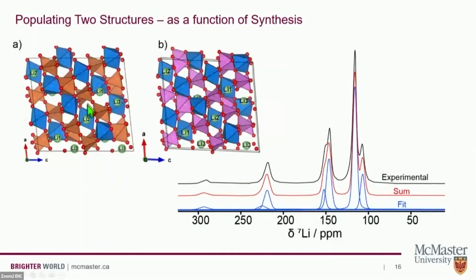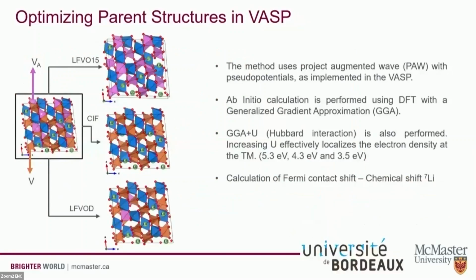The orange one is the original CIF file from our collaborators in Montreal, and the pink is if we fully populated this new set of sites that Tiana had determined in the crystallography. So in order to understand why those chemical shift differences are happening, we rely on VASP, and this is in collaboration with Danny Carlier's group.